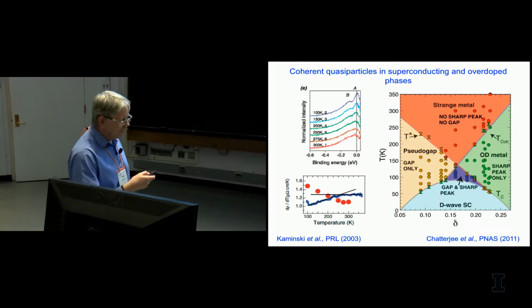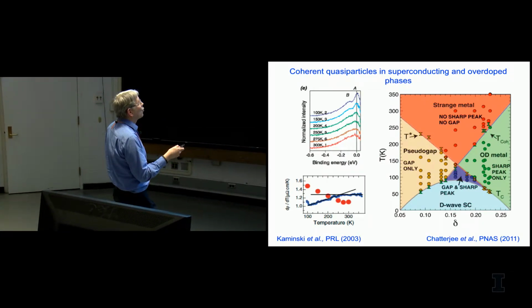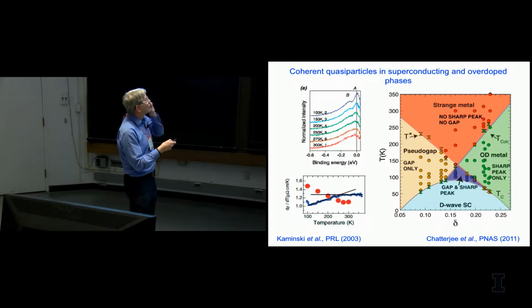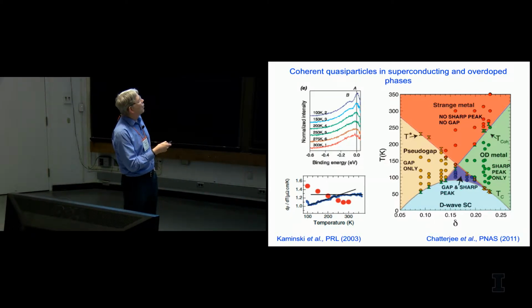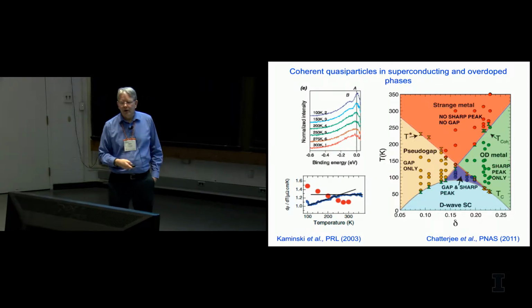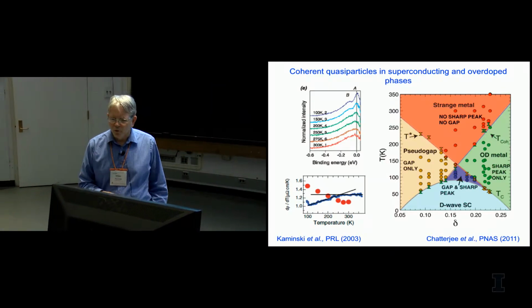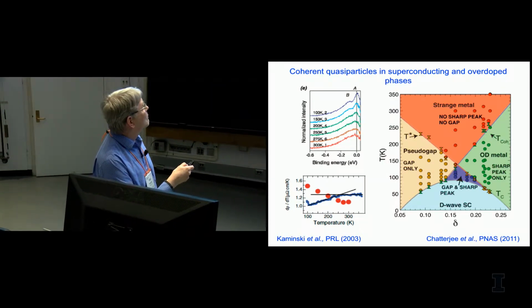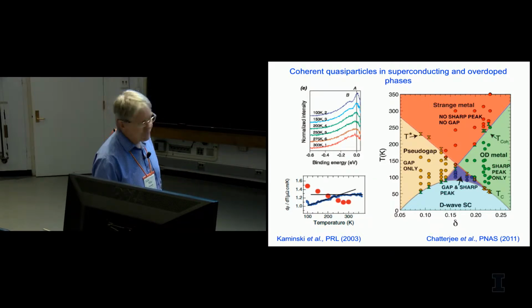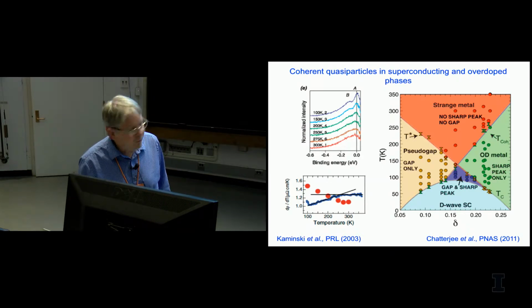And you can use things like angle resolved photoemission. This is again out near the antinodal region of the Brillouin zone where the superconducting gap is largest, and you can map out as a function of doping and temperature that in this region of the phase diagram you actually have coherent excitations. So you have coherent excitations in the overdoped phase and in the superconducting phase, but in the strange metal phase and in the pseudogap region of the zone, you have evidence for non-Fermi liquid behavior in the normal state. And this behavior of the strange metal phase where you have no spectral gap but you actually have no coherent excitations was understood early on.